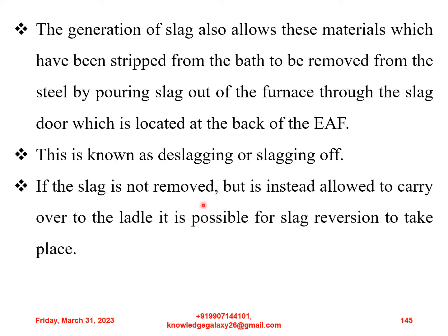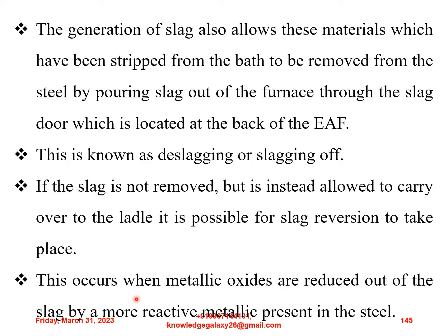If the slag is not removed but is instead allowed to carry over to the ladle, it is possible for slag reversion to take place. This occurs when metallic oxides are reduced out of the slag by a more reactive metallic present in the steel.